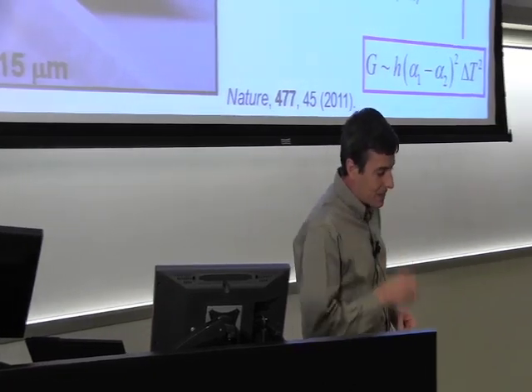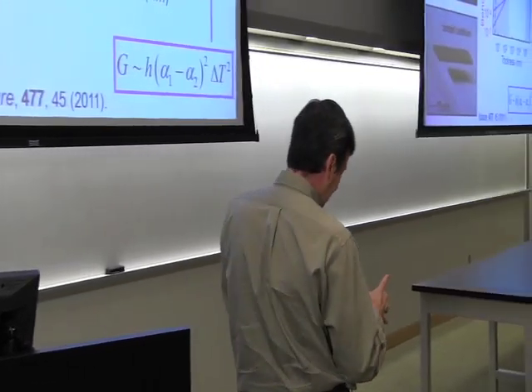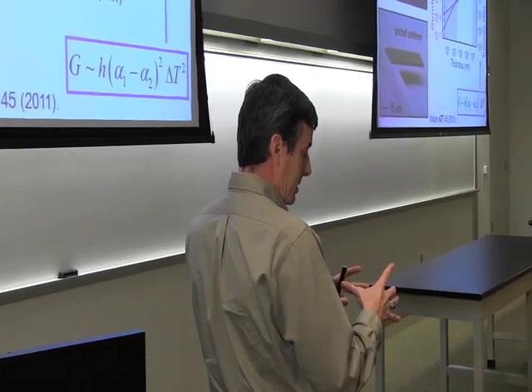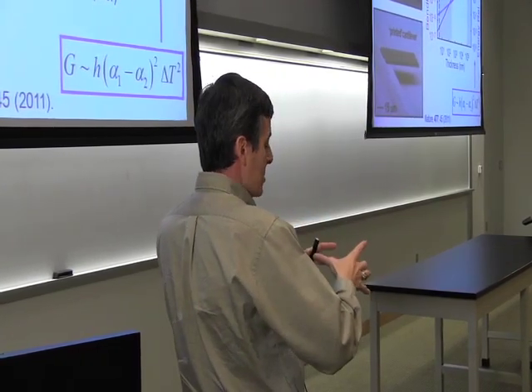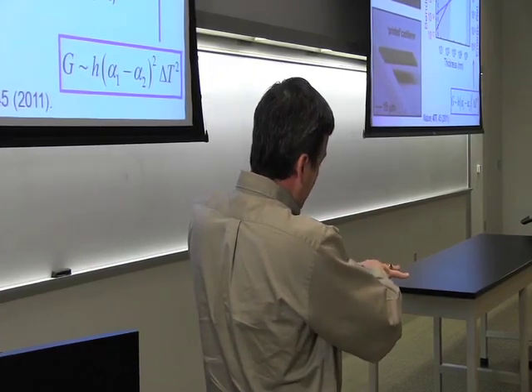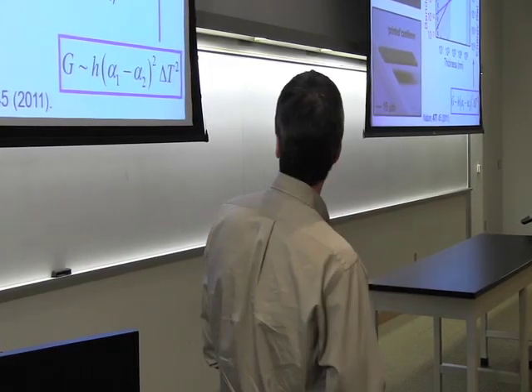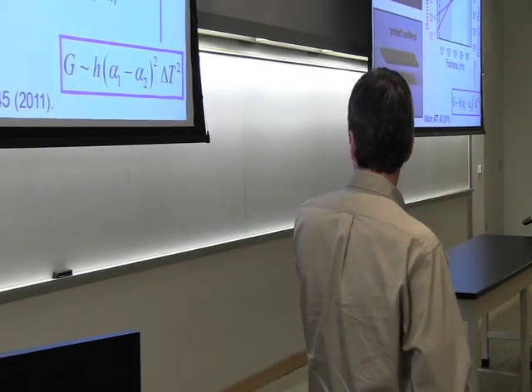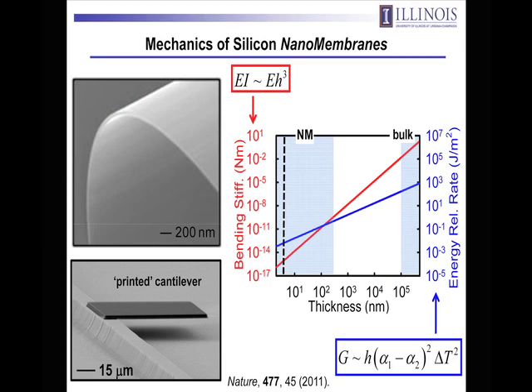And so if you think about the silicon wafer, it has its mechanical attributes partly because of the intrinsic properties of the silicon, but also because of the geometry of the structure. The wafer itself is about a millimeter thick. And if you think about the bending stiffness of a material, it depends not only on the Young's modulus of the material itself, but also the thickness. In particular, the bending stiffness, EI here, is linearly proportional to the Young's modulus. It depends on the cube of the thickness. And the consequence of that is pretty simple, but it's also profound if you think about the magnitude. So consider the silicon wafer geometry is maybe a millimeter thick. The bending stiffness in that case, with 150 gigapascals for the Young's modulus, is about 10 newton meters.